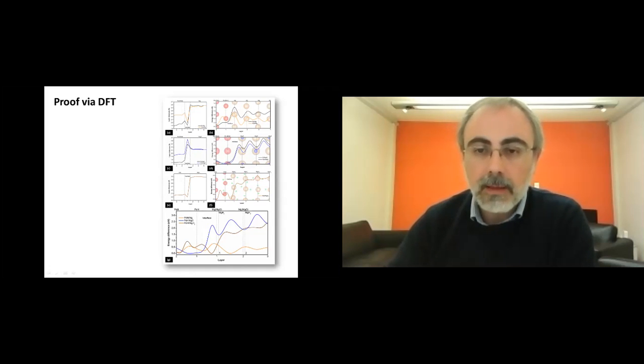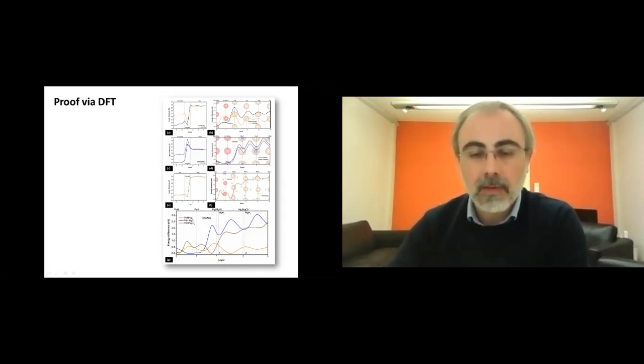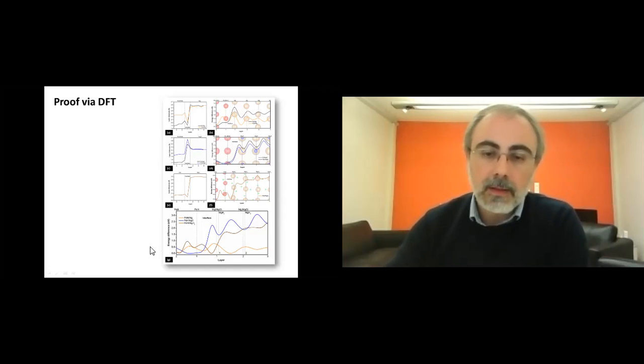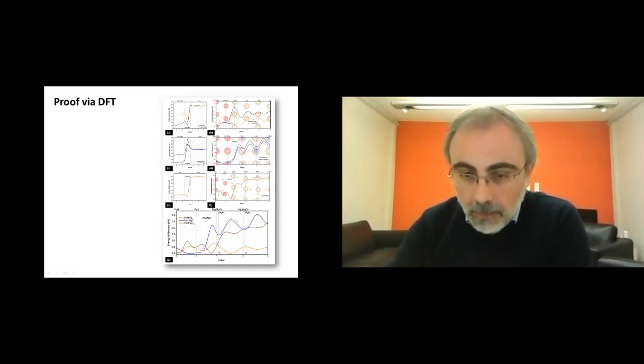And when you take these barriers and put them all in the same graph together at the bottom, you can see that there is in principle practically no barrier for hydrogen to penetrate the palladium-magnesium metallic interface. There is some significant barrier between palladium and magnesium hydride, the one in the graph here.